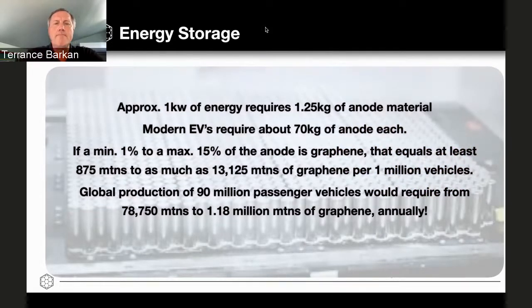If you look at and make the assumption, and these are just rough assumptions, but they're reasonable. About 1 kilowatt of energy requires 1.25 kilograms of anode material. If you look at a passenger vehicle, for an electric vehicle, it needs about 70 kilos of anode material. That anode material can have a range of content of graphene from 1% approximately to 15%.